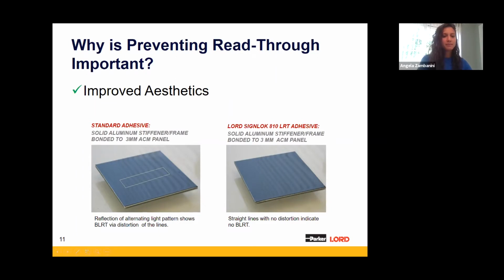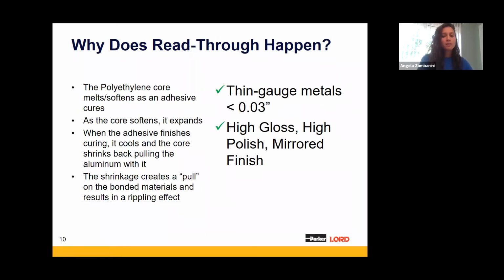Now, the materials that are subject to bondline read-through are thin gauge metals that are less than 0.03 of an inch thick, with a high gloss or a high polish or even a mirror finish. One thing we want to note is that the larger the panel or the darker in color it is, the more exaggerated that read-through effect tends to be, especially when it's reflected into sunlight. So the larger or darker the panel, the more read-through you could potentially see.